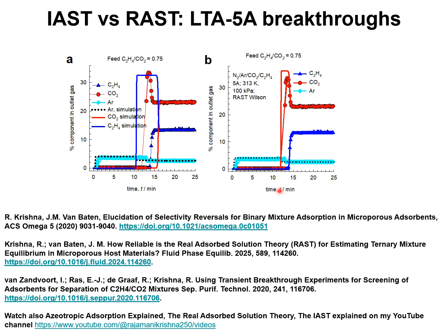However, the experiments reported by von Zandvoort and others, including myself, and reported in Separation and Purification Technology in 2020, show that LTA-5A could also be a candidate adsorbent, provided the feed mixtures are significantly leaner in C2H4 with respect to CO2, as is the case in the OCM reactor products.